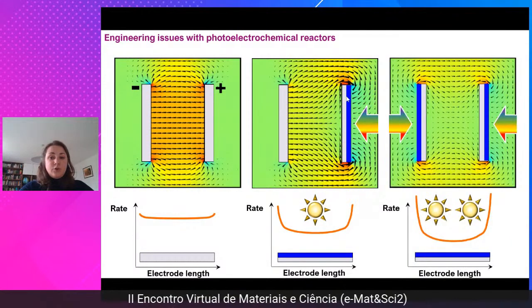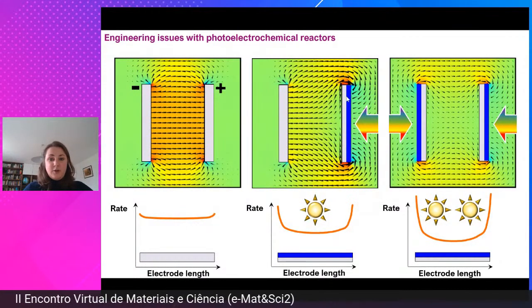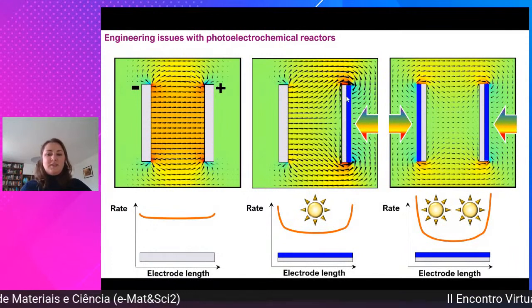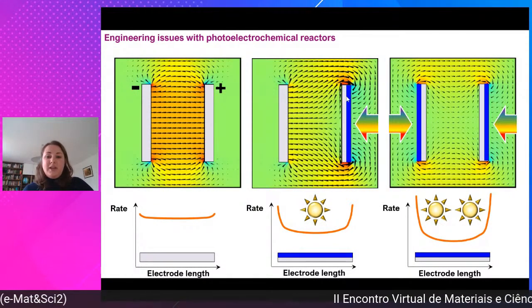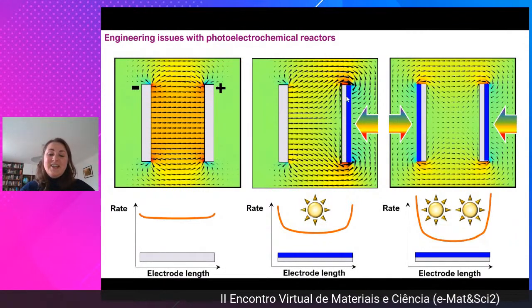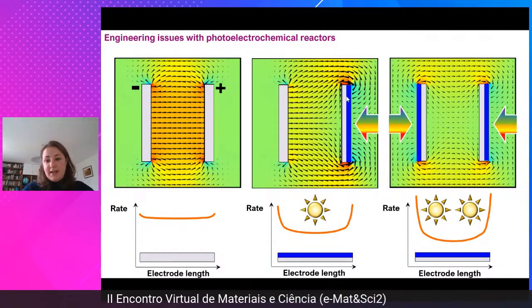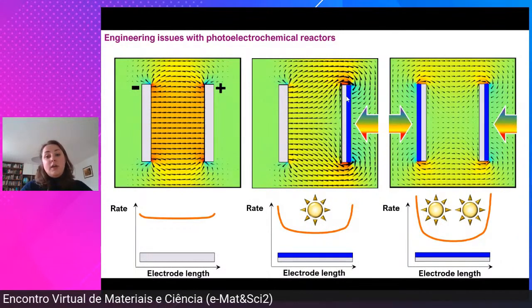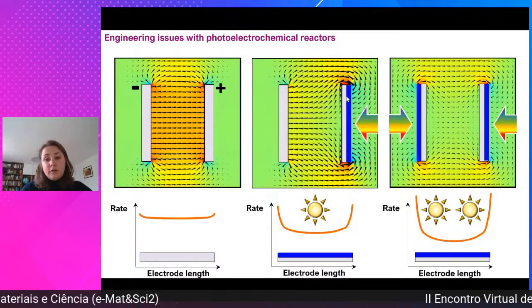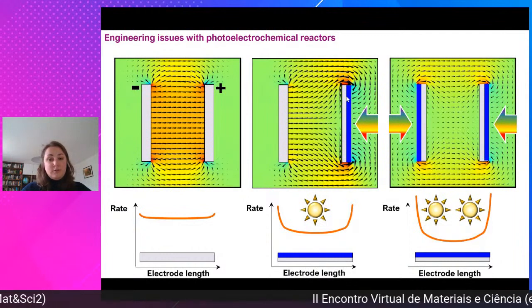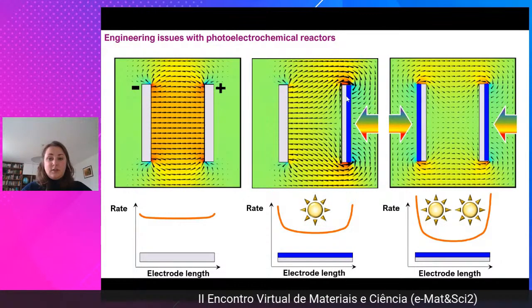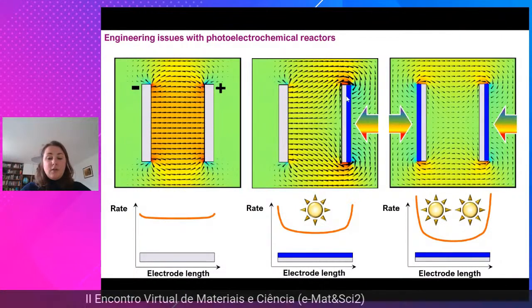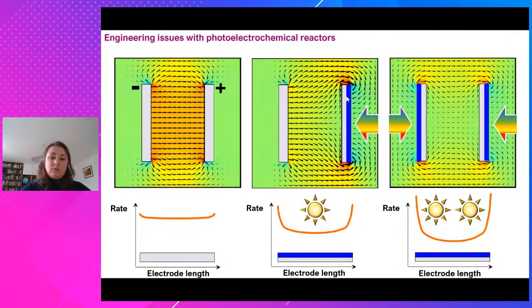And if you happen to want to use a photoanode and a photocathode, and this is like an extreme case scenario where you need to orientate both of your electrodes to face the outside of the reactor, the scenario is exacerbated even more. So the extent of the losses that occur due to these non-uniformities depend on some factors. They depend on the resistance of the electrodes. They depend on the conductivity of the solution, but they also depend on the magnitude of the current density that's actually being generated.